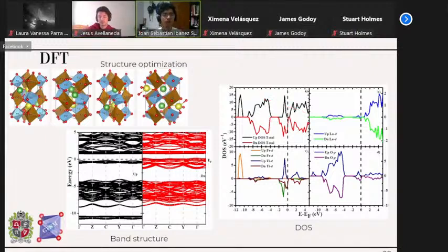Yep. So with the help of Chris Sotelo from Universidad del Norte, we actually made some calculations of the structure and the electronic properties of our structure. In particular, we solved the Kohn-Sham equations by a plane wave method using the VASP software. The plane waves had an energy cutoff of about 520 electron volts, and we used a mesh of k-points in the reciprocal lattice following the scheme made by Monkhorst and Pack, with a mesh of 7 times 7 times 5. The calculations were performed following the generalized gradient approximation, and the exchange correlation energy was treated by the Perdew-Burke-Ernzerhof scheme. And in particular, given that we were working with iron, we added a Hubbard correction of 5.3 electron volts to the orbitals of the iron cation.